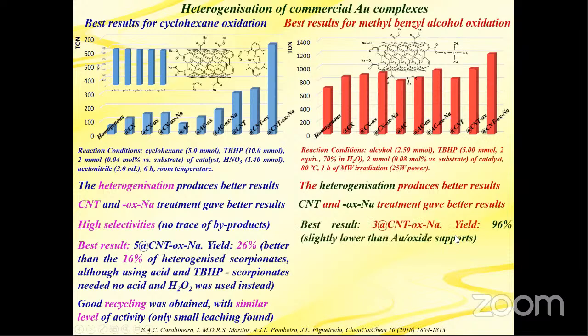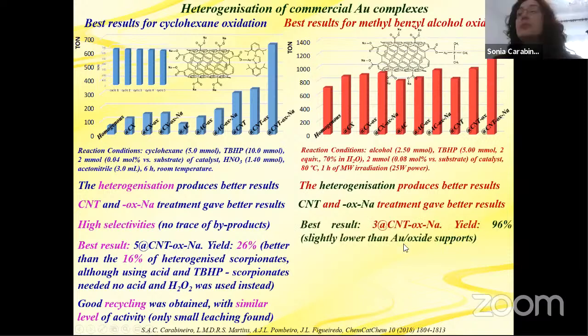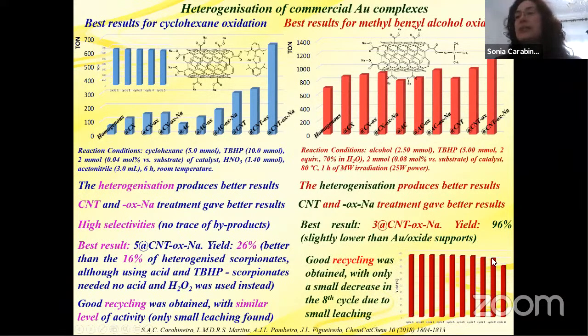And we obtained 96% yield, that was slightly lower than gold on oxide supports. And still good recycling was obtained, see, up to 10 cycles, with only a small decrease here in the 8th cycle, and then just due to a small leaching only up to this cycle. So it's quite good that we heterogenize, because complexes can be reused again, and if it was homogeneous, no.